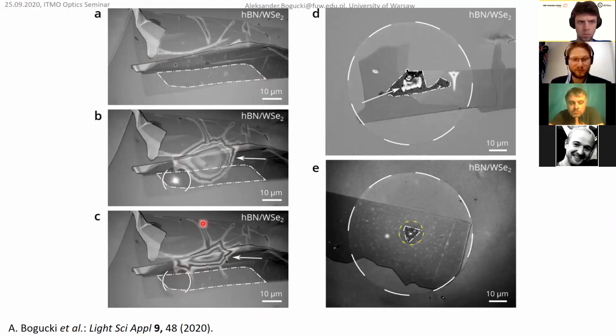However, some destructive wave region appeared, and this is another example on the right side. So our flake is again the dashed line, and we can see there are bubbles of resin, probably due to changing interference conditions. So the recipe for good printing was just to have flat hBN, so you don't have really high steps of hexagonal boron nitride. Everything is flat, and we were also not printing directly over the flake. We made a very small cavity, just 1 micrometer high, which was unpolymerized. Then after all the printing and developing, we shone ultraviolet light on it just to be sure that it was polymerized. And then no bubbles occur and everything is fine.